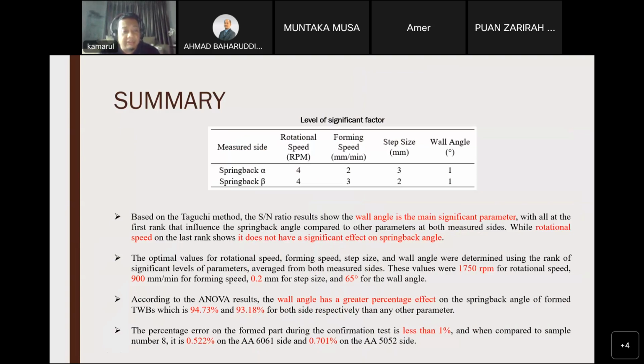Okay, then according to the ANOVA result, the wall angle has the greatest percentage effect on the spring back angle of the formed tailor-welded blank, which is 94.73% for the spring back on 6061, and 93.18% for the 5052 side. That contribution is high because with ANOVA, we usually look for significance at 95%, so a contribution of almost 95% is very high.